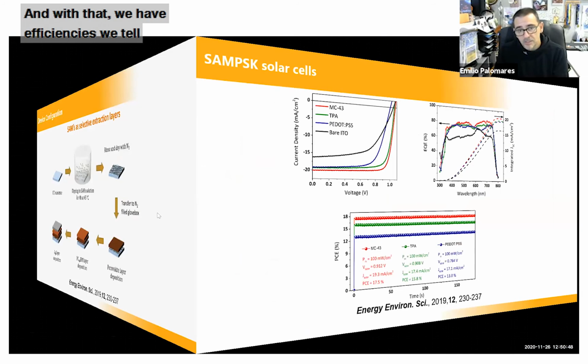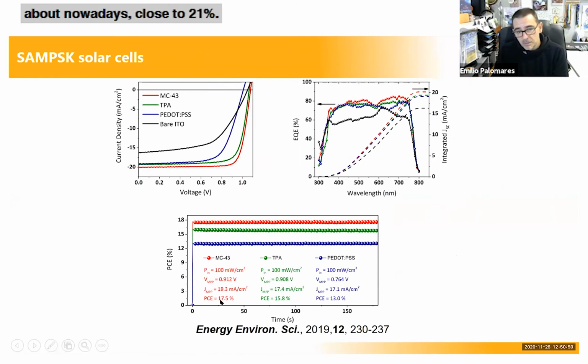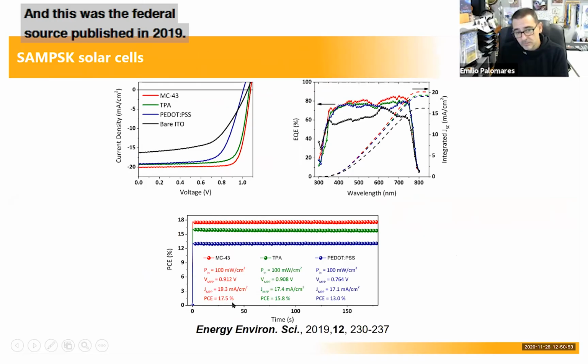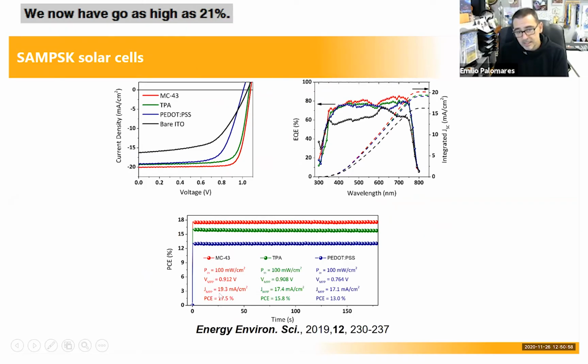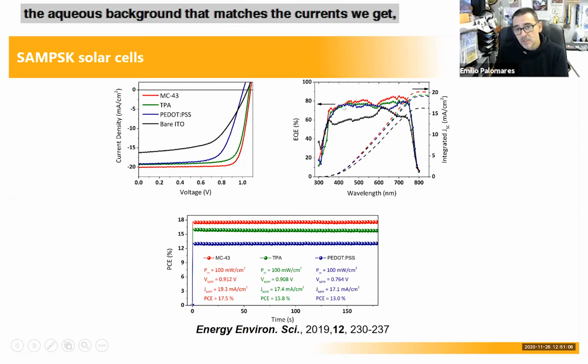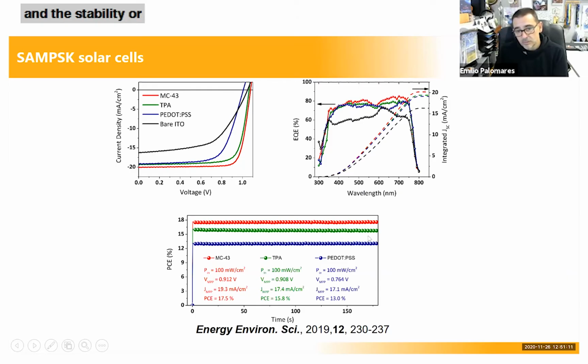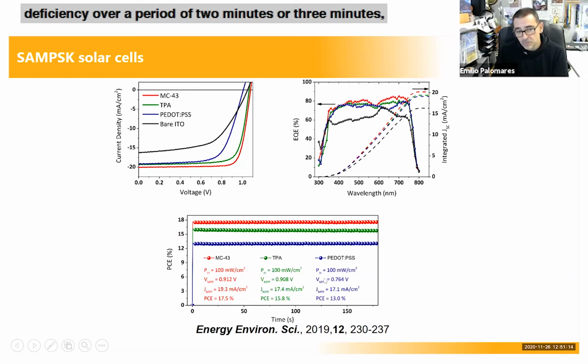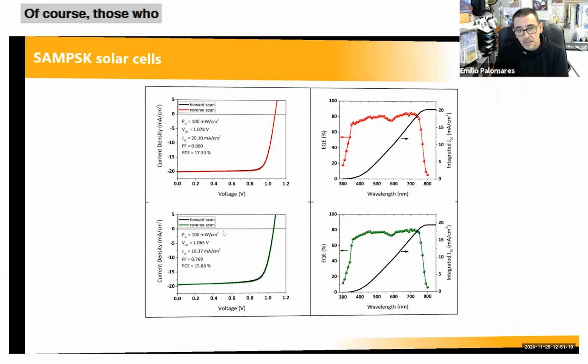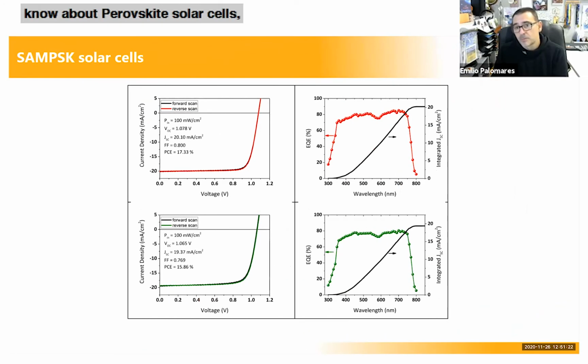And with that, we have efficiencies which are nowadays close to 21%. This was the first result published in 2019. We have now gone as high as 21%. And this is how the IV curves look. So we have the high voltage, we have the high current, the EQE spectrum that matches the current we get, and the stability or the efficiency within a period of 2 or 3 minutes, which is what we need to measure spectroscopy. Of course, those who know about perovskite solar cells will have heard about the hysteresis process.